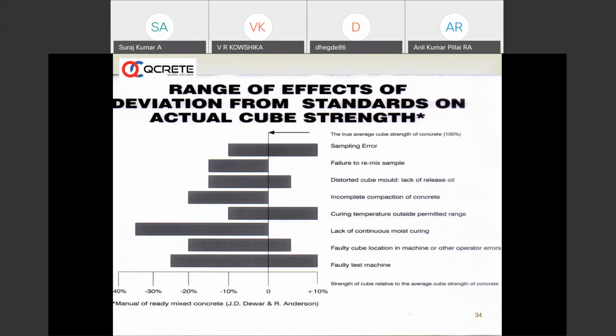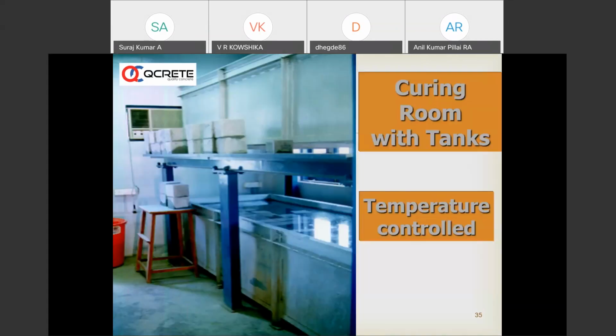We need to keep the structure cooler. We need to do ponding on structures, at least as IS describes. You need to cure, especially if you are blending with fly ash or GGBS, 14 days is a must. I know many times it is difficult in big projects, but we need to follow that. As far as the lab curing is concerned, we need to cure in standard condition, 27 plus or minus 2 degrees.